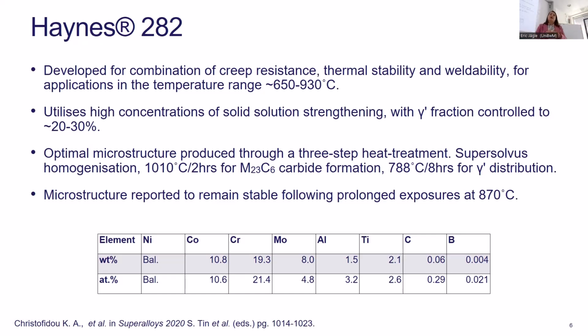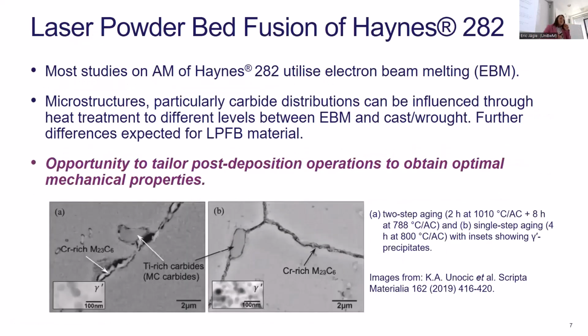So traditional cast and wrought Haynes 282 uses a super solvus homogenization at about 1150 degrees Celsius, followed by 1010 degrees Celsius for 2 hours to precipitate the M23C6 carbides at the grain boundaries, and then 788 degrees for 8 hours to optimize the gamma prime distribution. So quite a complex post-processing heat treatment for a nickel-based superalloy. And the microstructure is actually quite stable. So we don't see the formation of deleterious phases like TCP phases or excessive growth of the gamma prime either at temperatures over 870. And really looking at the composition of the material, it's quite remarkable that it doesn't do that. When I first looked at it, I was convinced it was going to be horrendous for stability, but it isn't. It's beautiful.